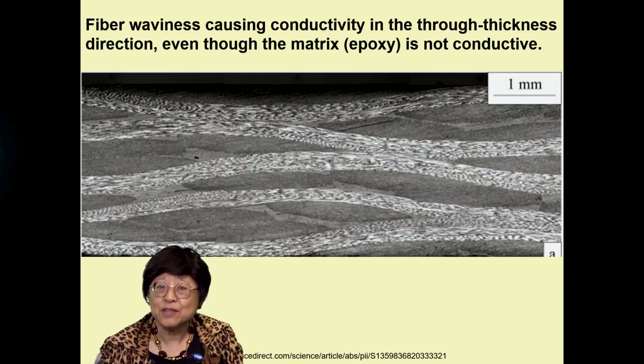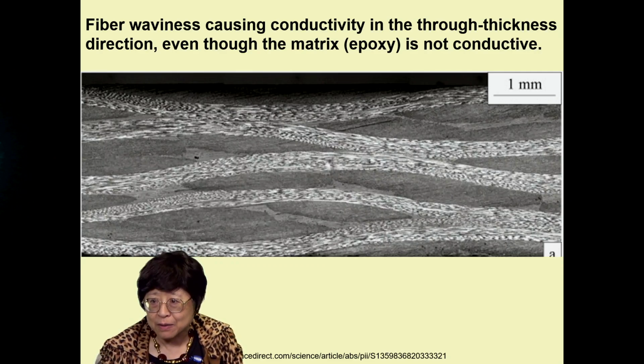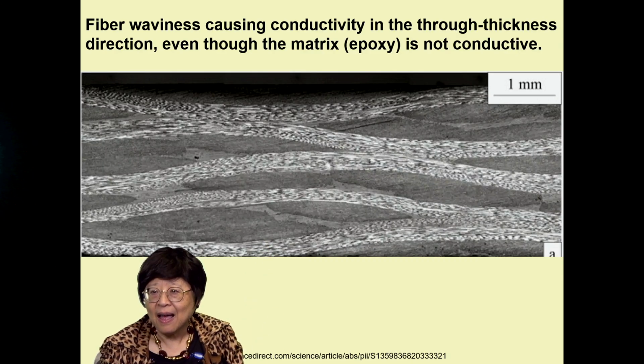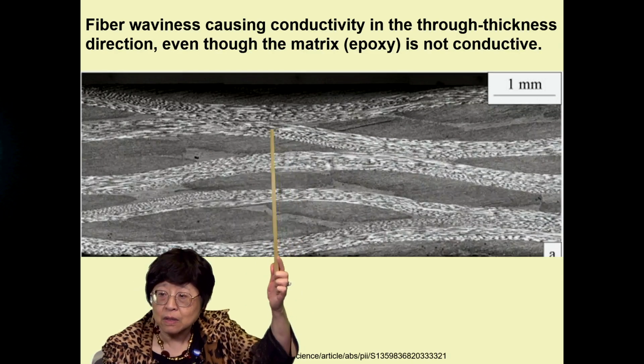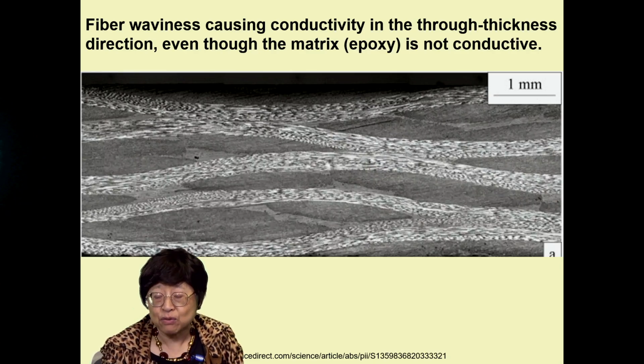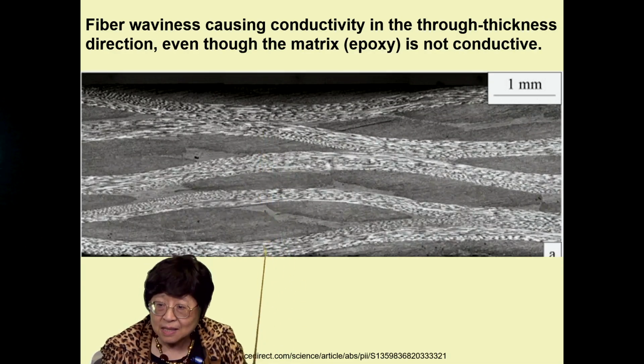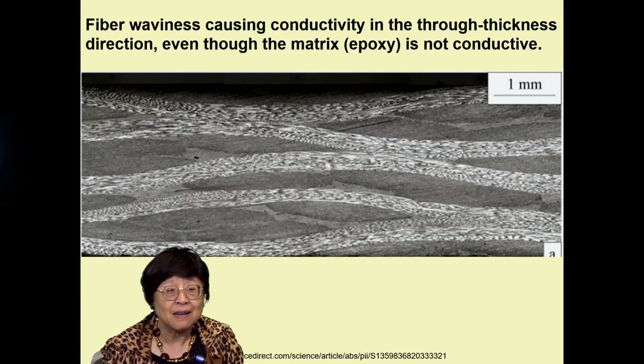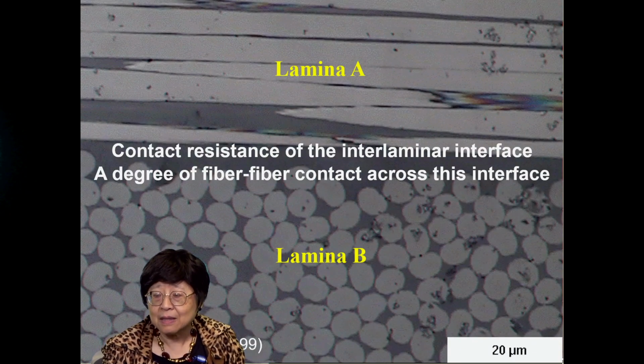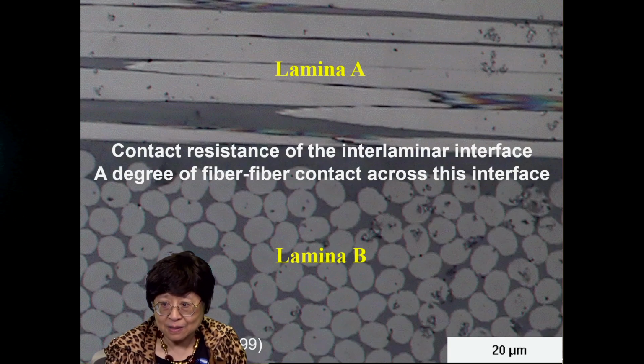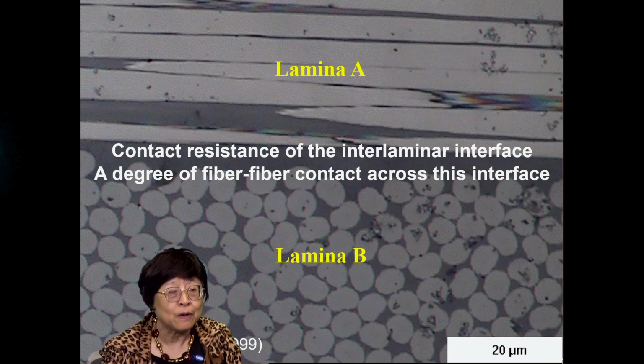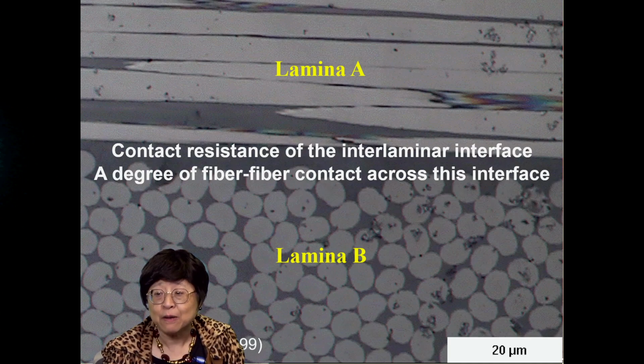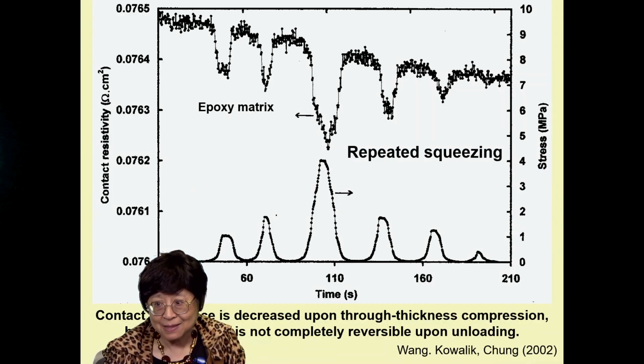Fiber waviness tends to occur in all these carbon fiber composites. You see the waviness. And the waviness causes conductivity in the vertical or through-thickness direction, even though the matrix, such as epoxy, is not conductive. And therefore, the resistance in the vertical direction is never infinity. And this contact resistance between the adjacent laminae reflects the integrity of that interface. This contact resistance is never infinity because there's a degree of fiber-fiber contact across this interface.